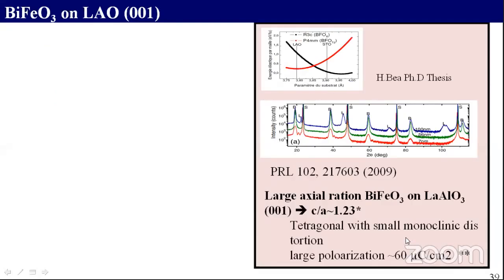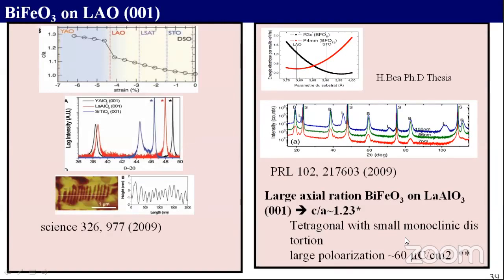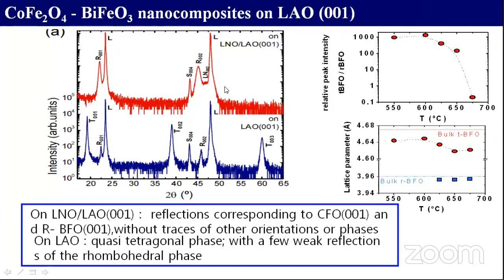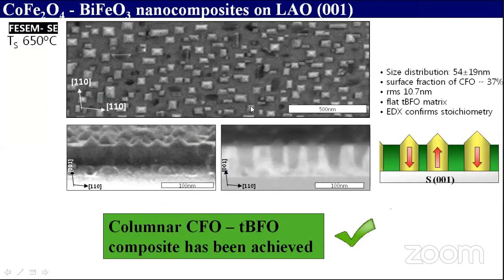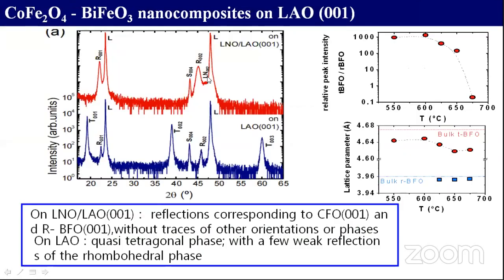But there are some theoretical reports and also experimental reports available for a single phase material that this is possible. This XRD plot shows a thin layer of lanthanum nickelate will produce a normal rhombohedral structure of bismuth ferrite. If you remove this lanthanum nickelate and grow your perovskite bismuth ferrite directly on the lanthanum aluminate substrate, you will have a very small rhombohedral structure, but a huge tetragonal structure comes out.